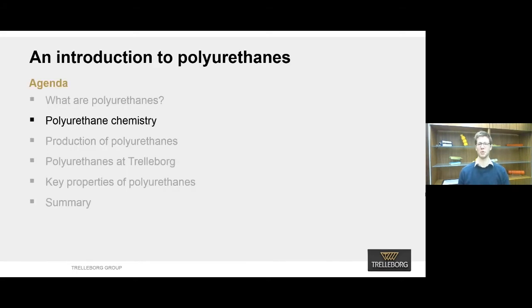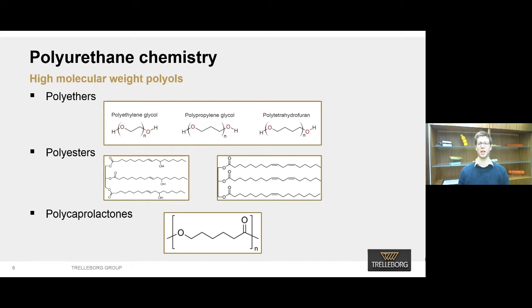Now I'll talk about the chemistry of polyurethanes. The starting point to all formulations are these long chain organic molecules with various molecular weights, which can vary from 400 to 4000 daltons. Over 70% of a complete polyurethane structure can be one of these materials, so picking the right one is ideal when you look at the end application. For example, polyethers are used in subsea applications due to their excellent hot wet properties, polyesters are used in mining components due to their high abrasion resistance, and polycaprolactones are used in dynamic applications due to their fatigue endurance.